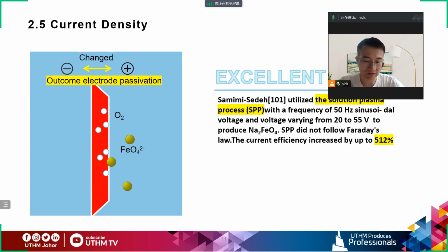The first factor is the current density. The impact of the current density is not only related to the magnitude of current density, but also to the way the current is operated. Increasing current density permits the generation of ferrate, but at high current density, more oxygen is produced at the electrode. Meanwhile, the increase in temperature due to current density at the electrode accelerates the decomposition of ferrate. Changing the method of the current application can reduce the likelihood of electrode passivation and improve current efficiency.